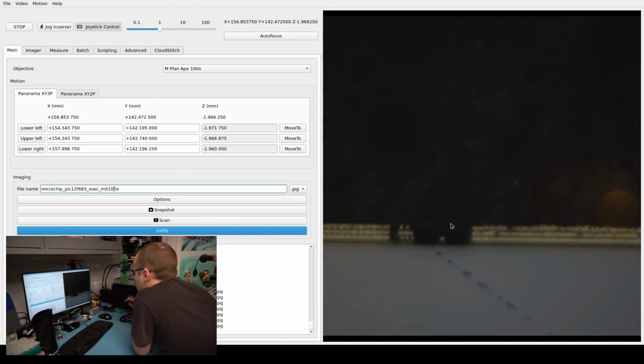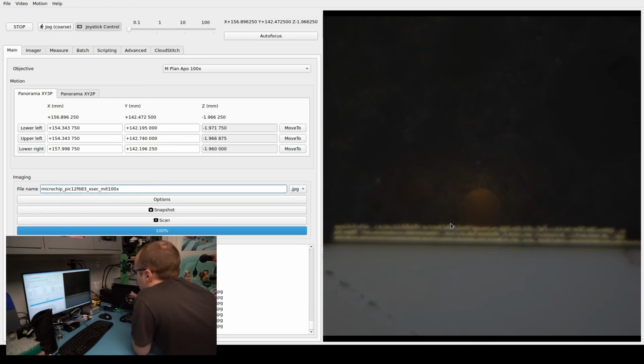And now we're looking at another ball bond that is a little bit further into the sample because the polish was not perfectly level, so we can see that we're still in the bond pad. We've got all 3 metal layers visible, but we haven't actually got into the ball itself. It's still slightly buried through maybe 10-20 microns of molding compound.